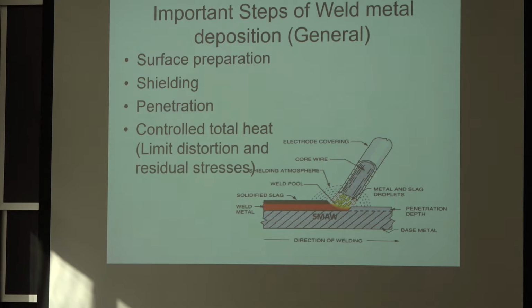So this is what we went over yesterday, that when you do fusion welding, you bring electrical energy, it melts the base material and also your consumable. Now, if we could spend a lot more time on welding, there are ways you weld where the electrode here, let's say it's a tungsten electrode, doesn't consume itself. So we call it autogenous welding, where you essentially are blending the two pieces you have without adding a filler metal, but you still need to protect against the oxidation. So that was something we emphasized yesterday, to shield that welding pool, and traditionally it's done with the slag.